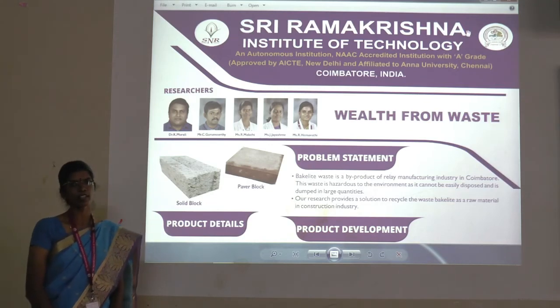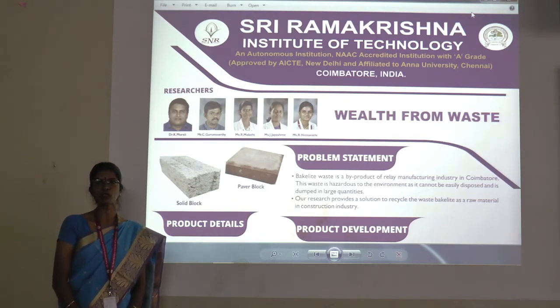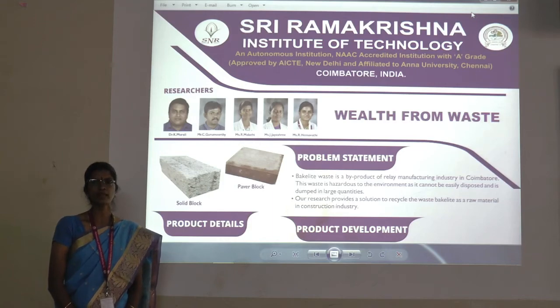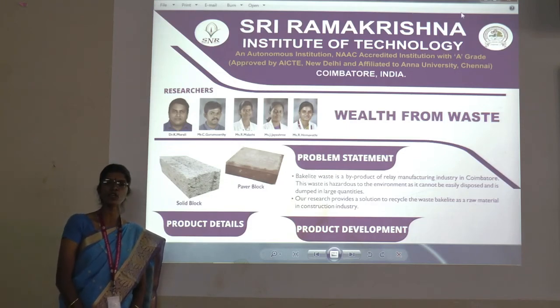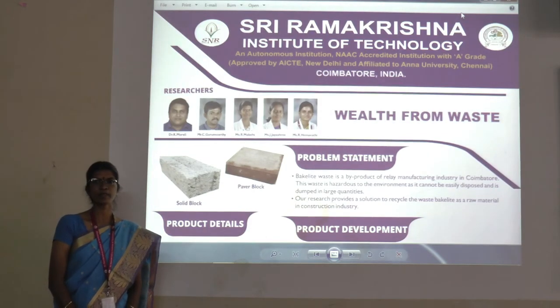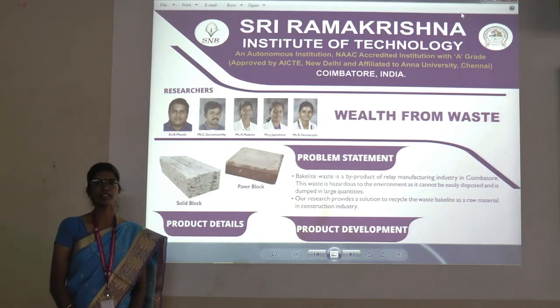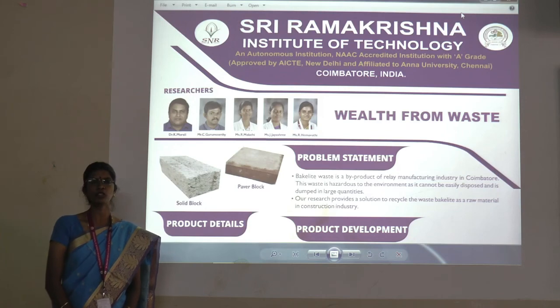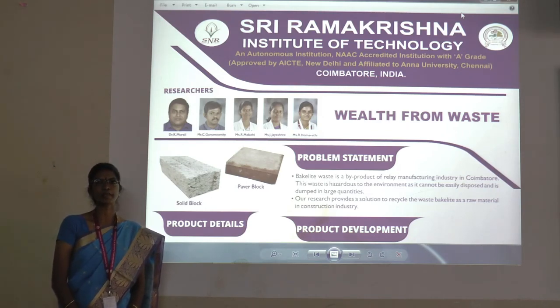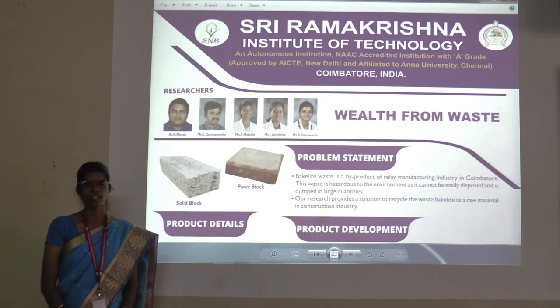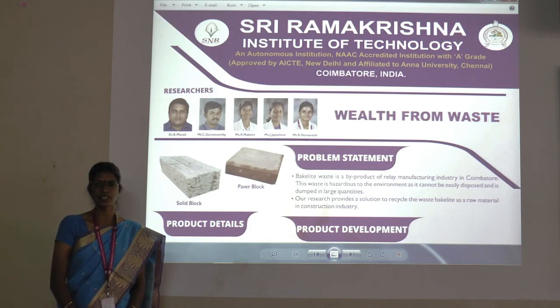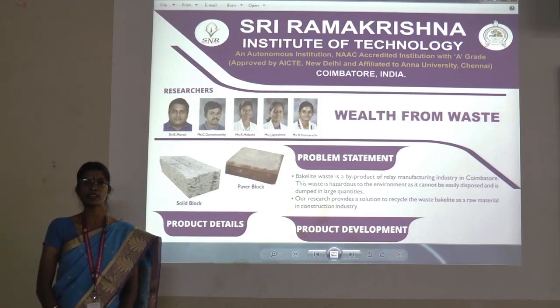Finally, in conclusion of this project, the optimum binder content is determined on the addition of 10 to 20% waste Bakelite in the bituminous mix. The stability, flow values and Marshall coefficients also increase with the addition of waste Bakelite at 10 to 20%. In these studies, from the standard coarse aggregate and fine aggregate tests, it is proved that waste Bakelite can be used as aggregate in flexible pavement. After testing the specimens, it was found that the optimum binder content, stability and flow value are achieved with the addition of 20% waste Bakelite in the bituminous mix. As a final conclusion and alternative choice in the construction field, it is recommended that waste Bakelite be shredded into smaller pieces and used in laying flexible pavement.